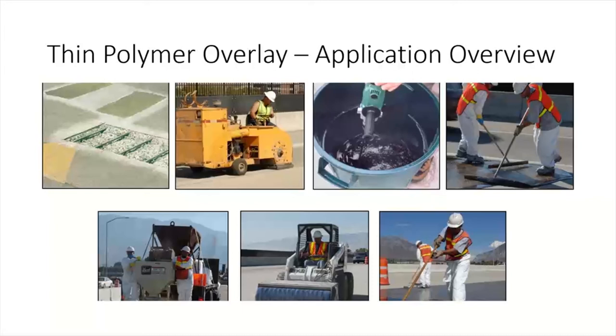One thing they did is they removed concrete below the rebar. And that's always recommended, so at least you can stick your fingers underneath there. And you've got some nice edges and it's a real rough profile. You got some shot blasting. You got a very basic method of mixing, and a very basic method of spreading aggregate. Like I said, any maintenance crew can learn how to do this.